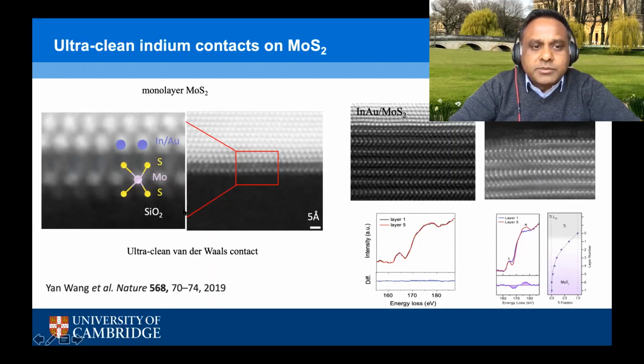We take the EELS measurements by focusing the TEM probe onto the sulfur atom. We measure the EELS spectrum and we get this black curve. Then we take a multilayer sample, go down to the fifth layer, focus our probe on a sulfur in the fifth layer, and we find that the spectra are very similar. EELS gives you information about the electronic state of the atom, and we see that electronically, the sulfur atom right next to the interface and the sulfur atom in the fifth layer down are no different.